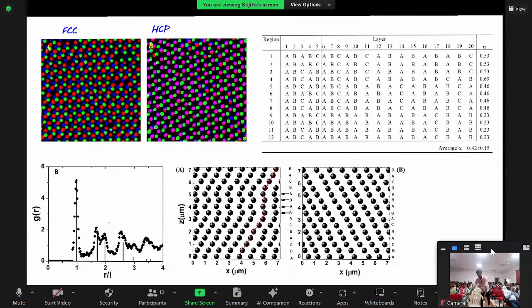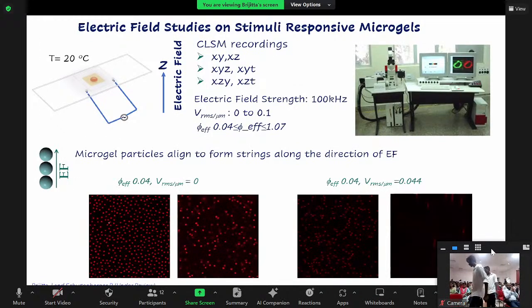So now coming to the electric field studies, which is the main title of the presentation. We take this microgel suspension, take a few microliters of it, put them in between a cover slip, and then apply electric field. Put these particles somewhere here in the microscope and study in the XY plane, XZ, XYZ, in time and along the Z axis how the particle dynamics changes. So we applied an electric field strength of 100 kilohertz and then varied the volume fraction. So we take dilute samples to highly concentrated samples.